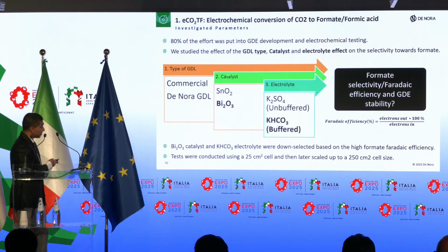Let me focus on the catalyst and electrolyte first. We screened tin dioxide and bismuth oxide as catalyst candidates, and also potassium sulfate, which is an unbuffered electrolyte solution, and potassium bicarbonate, which is a buffered electrolyte solution. What we realized when we combined bismuth oxide and potassium bicarbonate electrolyte was that we started noticing high formate Faraday efficiency. So we down-selected these two.